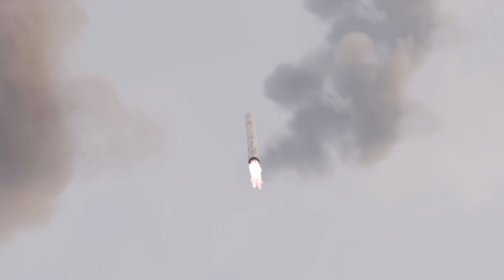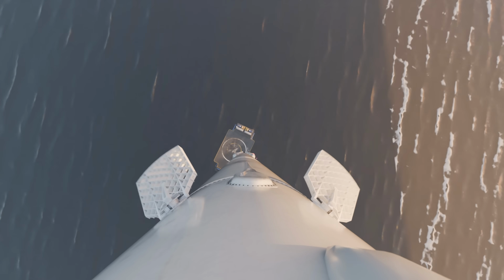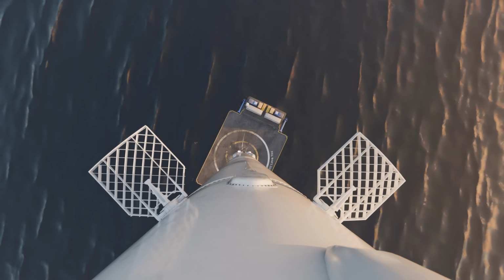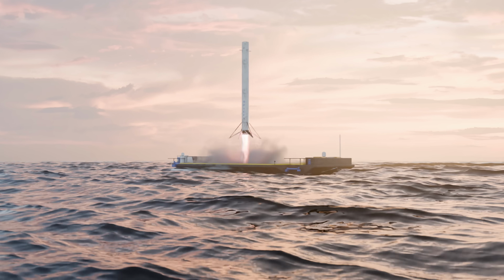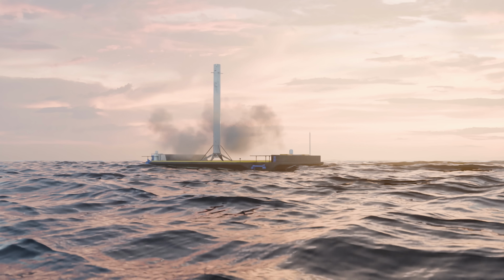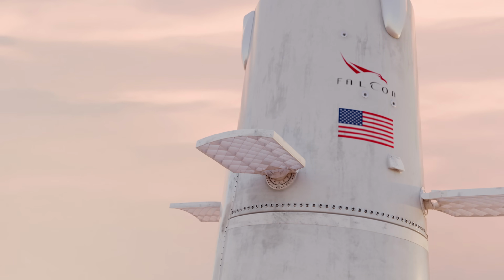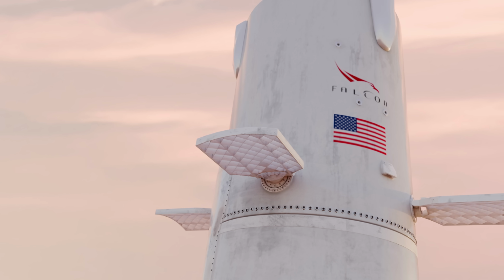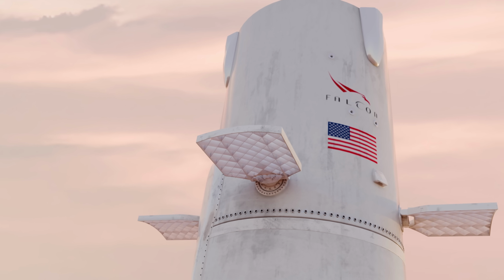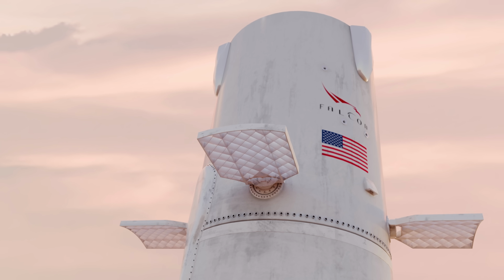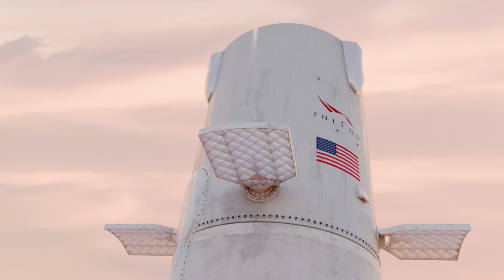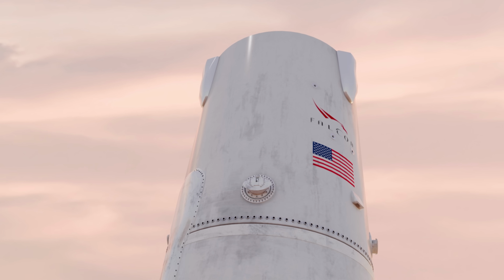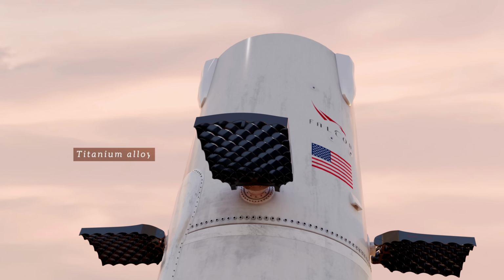When SpaceX engineers were first designing the Falcon 9 rocket, a key challenge was figuring out how to guide the booster back down to Earth. They decided to use grid fins, small gridded control surfaces that help steer the booster during descent and landing. At first, these were made from an aluminum alloy, but engineers soon realized the material wasn't quite up to the job. Although it was very light, it only barely withstood the intense aerodynamic heating experienced during descent. They eventually made a change, swapping out aluminum for a titanium alloy that could survive the extreme heat over and over again, unlocking true reusability.